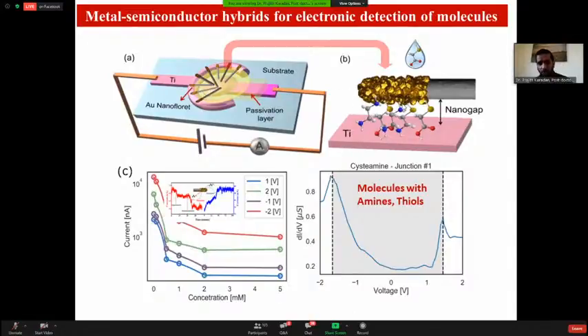In these studies we used molecules which have more affinity towards gold, like amines or thiols. They go and directly bind to the gold part of the nanofloret, and whenever we apply a current, it tunnels through the molecule. This is a kind of nano junction formed at the edge of the nanofloret and the titanium electrode. When we apply a current, the electrons tunnel through the molecules, reach the other junction, and are collected by the counter electrode.